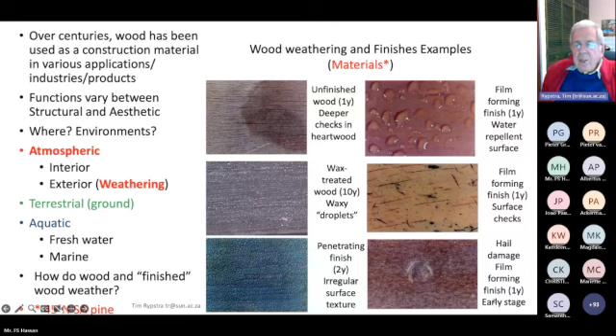The one on the right-hand side, a piece of coated wood, is still in relatively good condition after 1 year, and you can see the water repellent surface is still very active with water droplets. Then the next one, a film forming coating: the little cracks that appear there are a result of surface checks underneath. In other words, the moisture excluding function of the coating shouldn't be as it is at this stage. The protection against water or moisture penetration that it should give is not sufficient.